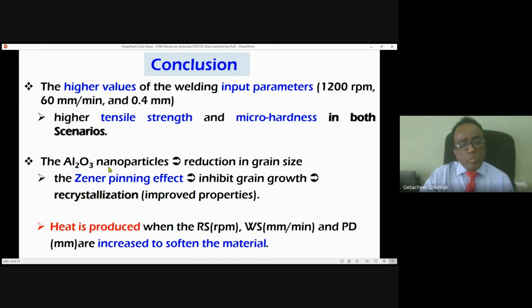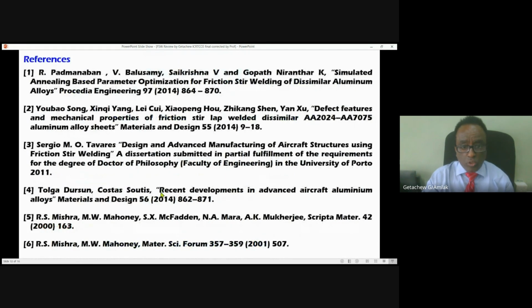The main reason behind this improvement or augmentation is the reduction in grain size due to this addition, and the other is the Zener pinning effect, hole pitch effects, which is the real reason for the inhibition of grain growth. So that's the reason for the crystallization process. The heat produced causes the smooth flow of materials from the leading side to the trailing side of the cutting tool.